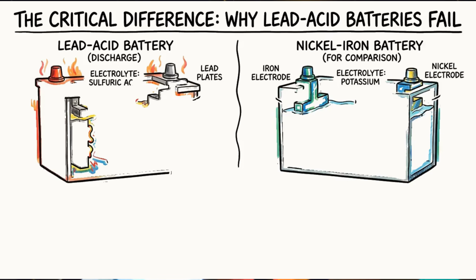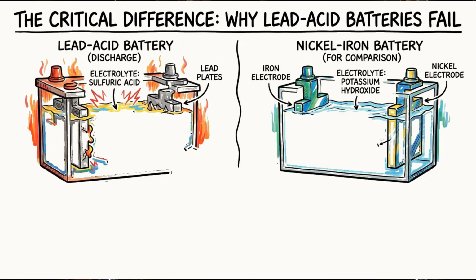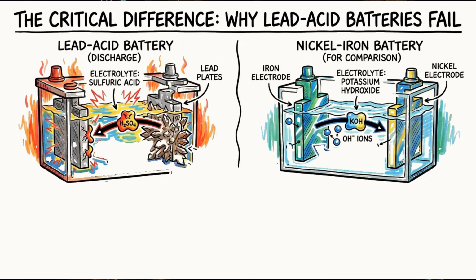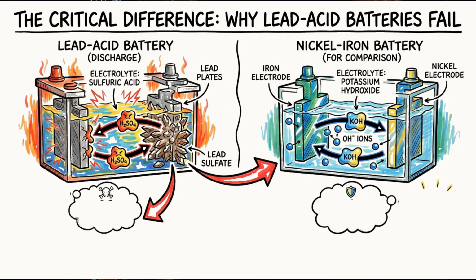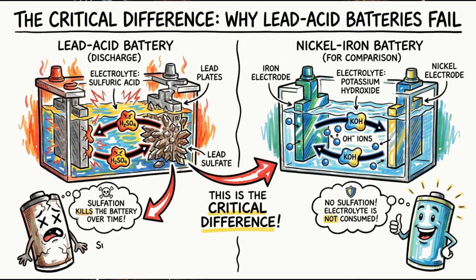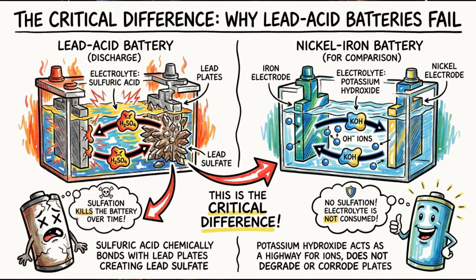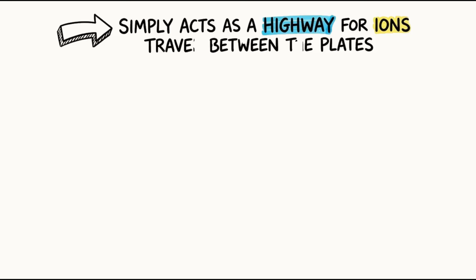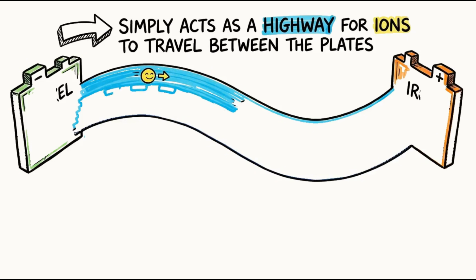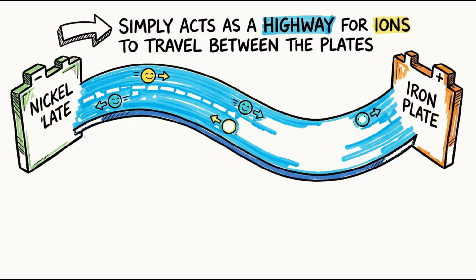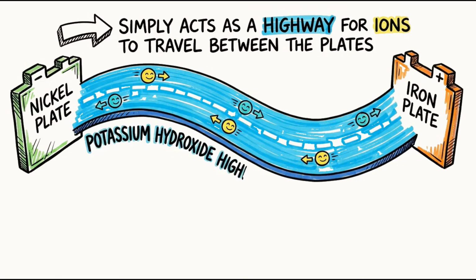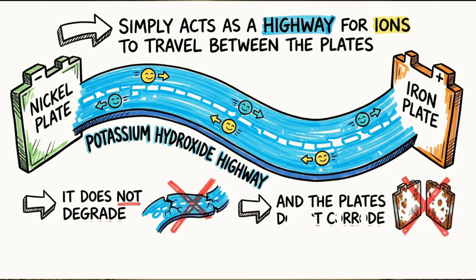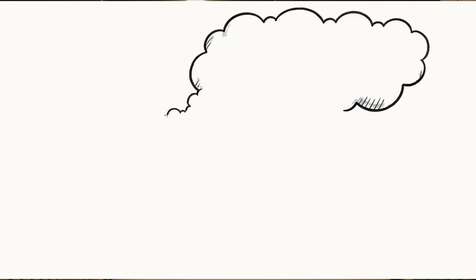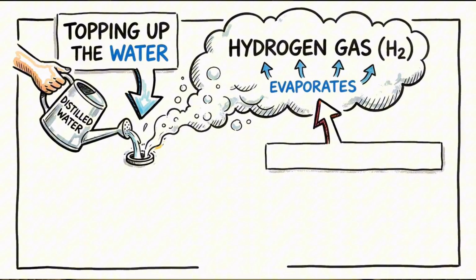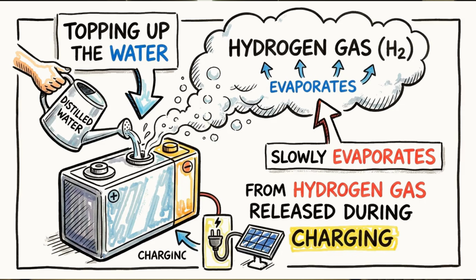This is the critical difference, because in a lead-acid battery, the electrolyte is sulfuric acid that chemically bonds with the lead plates during discharge, creating lead sulfate. And that sulfation is what kills the battery over time. In a nickel-iron cell, the potassium hydroxide simply acts as a highway for ions to travel between the plates, and it does not degrade, and the plates do not corrode, and the only maintenance is topping up the water that slowly evaporates from hydrogen gas released during charging.